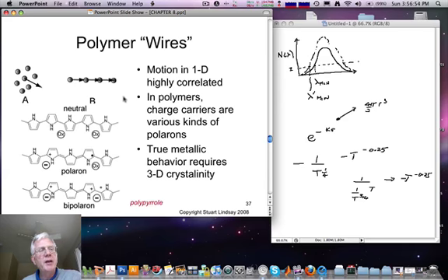However, chemists will recognize this as simply the motion of chemical bonds along a polymer, and let me illustrate this here for the case of polypyrrole, illustrated here. Polypyrrole becomes a conductor when an oxidizing agent is mixed into the bulk, as shown here. In that case, the chain can lose an electron to the oxidizing agent. The result of this loss of an electron in removing a bond from this ring is to generate a new chemical structure in which a radical is formed at this point in order to stabilize the removal of an electron from the ring over here.